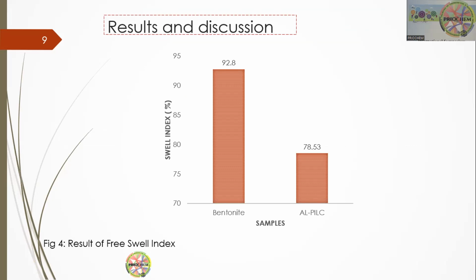For the swell index, we got 92.8%, and for that of the aluminum pillared clay, we got 78.53. And this is due to the replacement of the interlayer cations that are in between the aluminosilicate layers, because they are responsible for absorption of water. After the pillaring, that means some of the aluminum 3+ was able to exchange with the calcium, magnesium, and in some other cases, sodium.